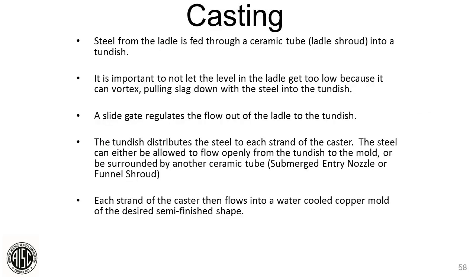So steel from the ladle is fed through a ceramic tube. We call it the ladle shroud. There's a couple important things there. You don't want to get the level too low, because you can actually vortex slag into the Tundish. So we actually shut our ladles off a little bit early to make sure we don't suck any slag into the Tundish that gets into the cast product. We use a slide gate to control the flow of steel. Think of a refractory metal slide gate. Gate valve, same thing. And like I said, the Tundish distributes steel to each strand of the caster, and it flows into a water-cooled copper mold into the desired semi-finished shape. Next slide, please.